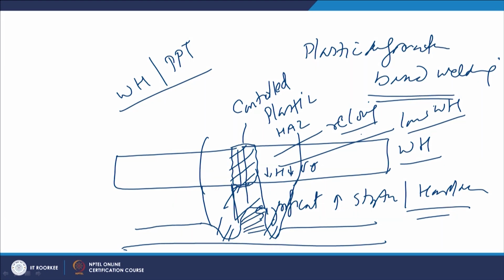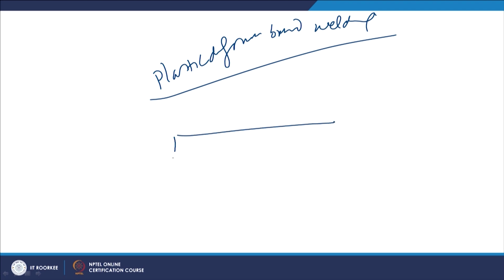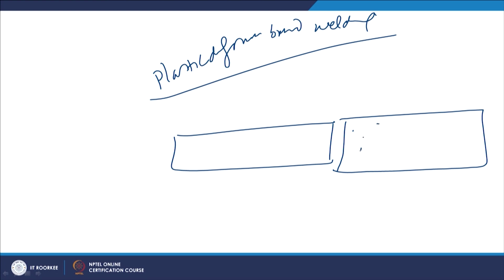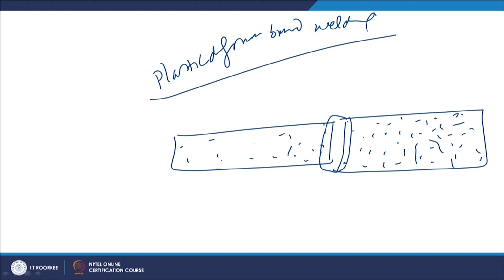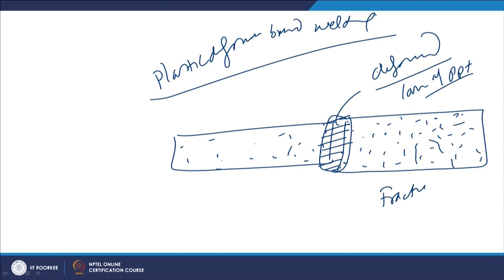On the other hand, if we talk about the plastic deformation based welding processes of the precipitation hardenable metals, where the presence of precipitates contributes significantly towards the increase in strength, then the response of the metal is like this. The zone next to the faying surfaces of the components, which are subjected to controlled plastic deformation for metallic continuity to develop the weld joint, is severely deformed during the welding process and experiences complete loss of precipitates, primarily due to the fracturing of all such precipitates.